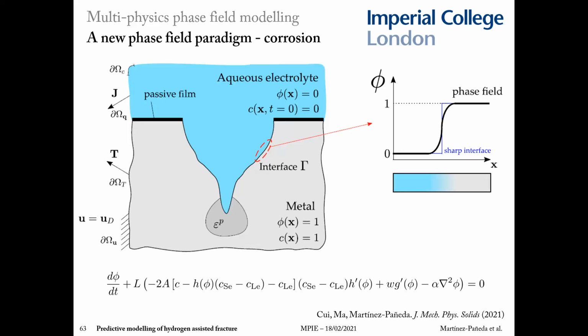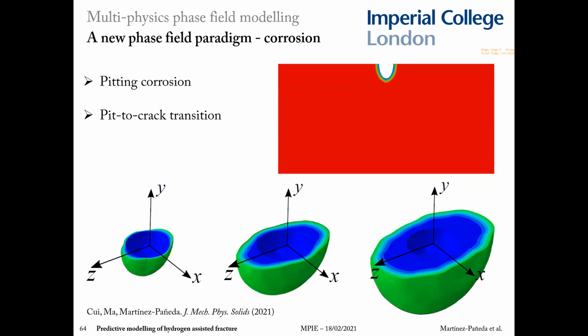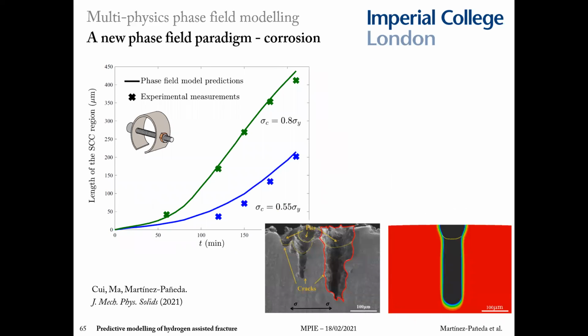I will only say that we have also incorporated into the modeling the influence of mechanics in corrosion kinetics and also the film repassivation and rupture process. And these are just some representative examples to show how the model can capture pitting corrosion and the pit to crack transition in both 2D and 3D. And we have validated our model predictions with experiments showing a very good agreement.